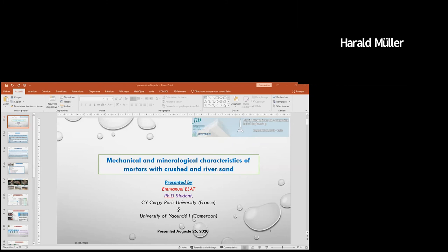Well, I would like to give a short comment. Emmanuel, thank you first for your presentation, which is an interesting approach. But some of your results raise some questions, and I have similar problems as Arnaud. If I compare the river sand with the crushed sand from a chemical and mineralogical point of view, there's only one big difference: the content of SiO2, this is quartzite. But quartzite is normally quite dense and has a pretty high strength. So this contrasts with your results.